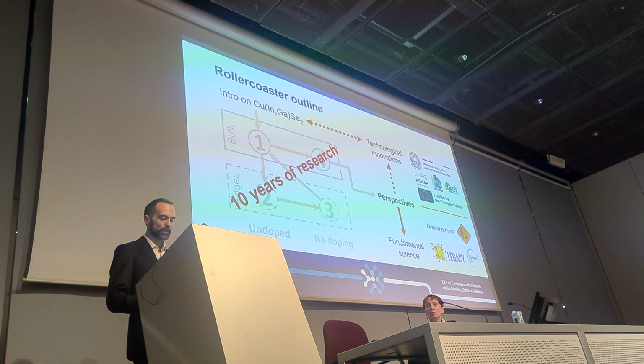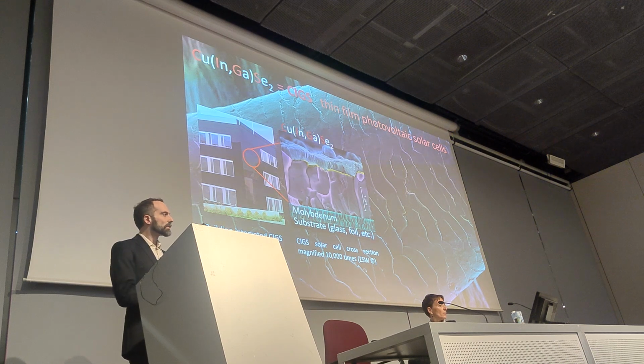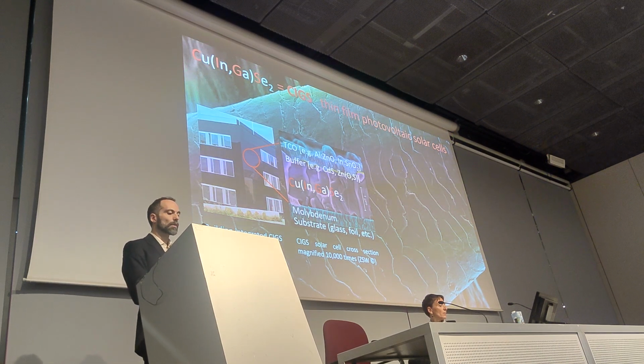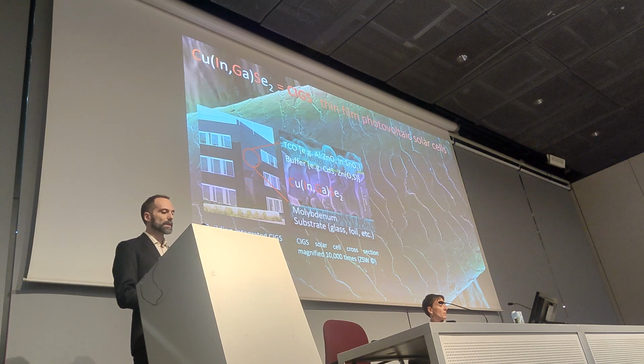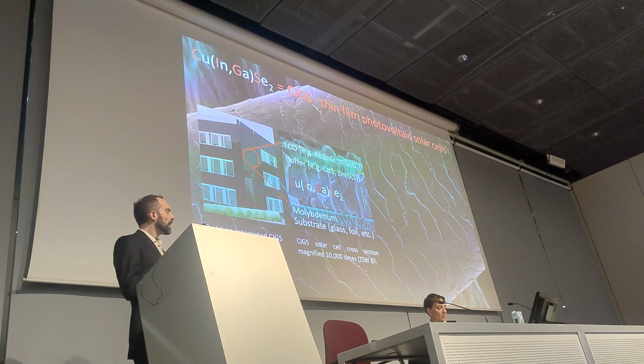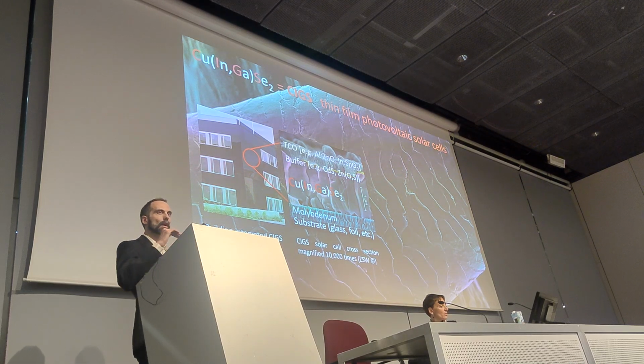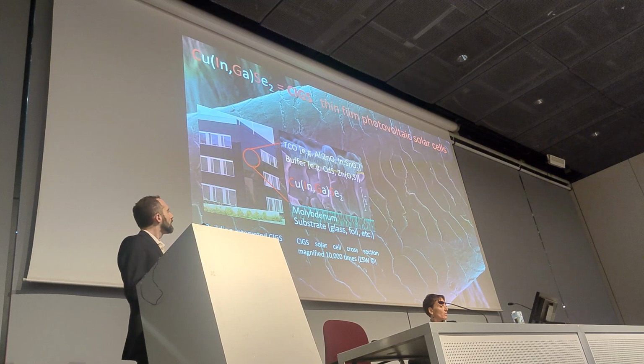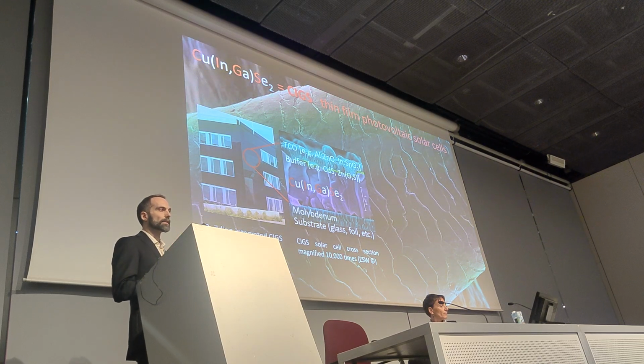So, CIGS solar cell technology belongs to the 2nd generation PV, also known as thin film. Here we see a structure of a solar cell. We start from a molybdenum coated substrate, on top of which we grow the CIGS material. The CIGS material is a p-type semiconductor, and we couple it with a very thin layer of n-type semiconductor that, together with the p-type, makes the p-n junction, the core of the solar cell. And on top of everything, we have a thin transparent conductive oxide that acts as the front contact, the window layer that lets the light through, but at the same time enables us to collect the generated electrons.